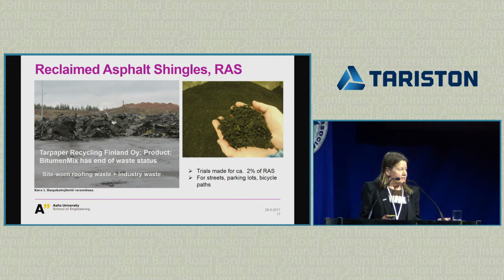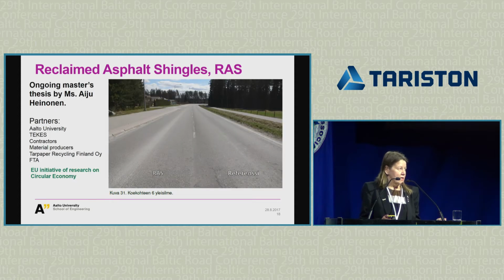And the other interesting thing we have been trying now is reclaimed asphalt shingles, the roofing shingles, and then industry waste is mixed and produced this kind of bitumen mix material that can be used. We tried about 2%. Of course, we need more long-term performance data, but at least for now, it looks good.